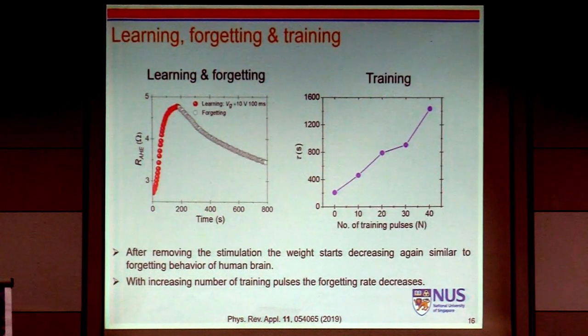We can also show learning and forgetting. We can keep sending our signal to the gate, increasing the potential. Once you stop gating, as time goes, the signal decays. So this is like forgetting, like our human brain. We can also show training, depending on how many pulses we initially give, 10, 20, 30, 40, and then we measure this relaxation time constant. If you train more, it decays slowly. So this is called long-term memory, and this is called short-term memory.